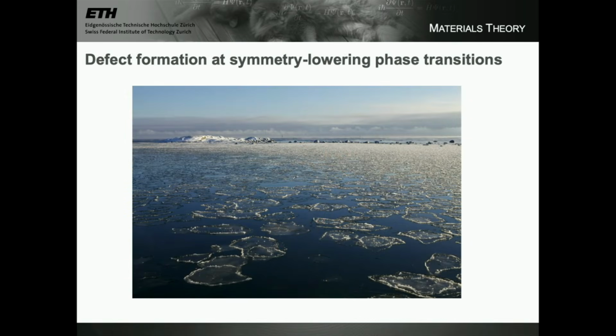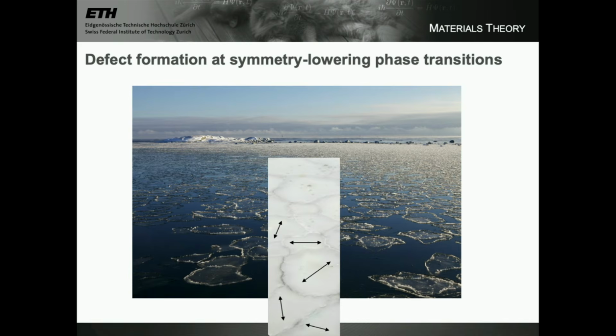Another feature of symmetry-lowering phase transitions is what's called defect formation. And again, the water to ice can illustrate this. And this is actually the Stockholm archipelago, and you can see that it's freezing. And so there are platelets of ice forming on the water, so the platelets of the low symmetry phase. And one region of the water may crystallize with one orientation, and another region of the water will crystallize with another orientation. And so when these regions meet together, there's a defect. In this case, it'll be a planar defect between the platelets of ice where they meet. So here's platelets which might have different orientations, and this defect formation where they meet.